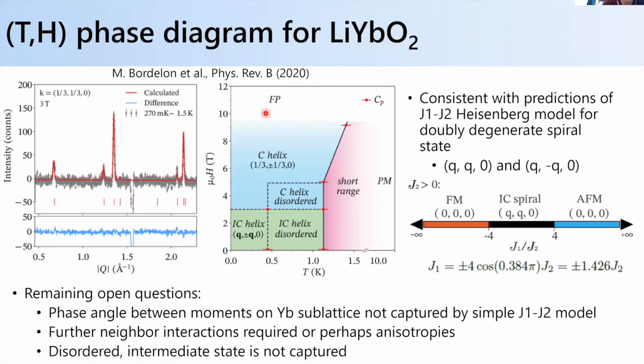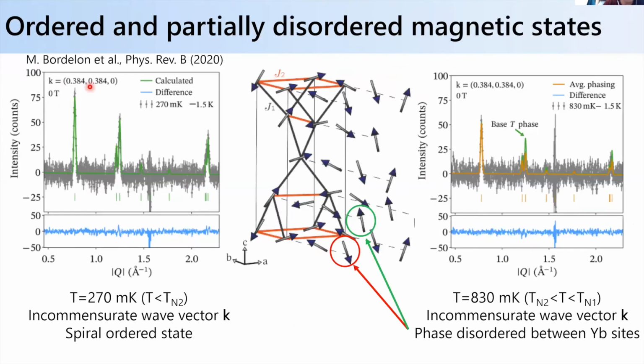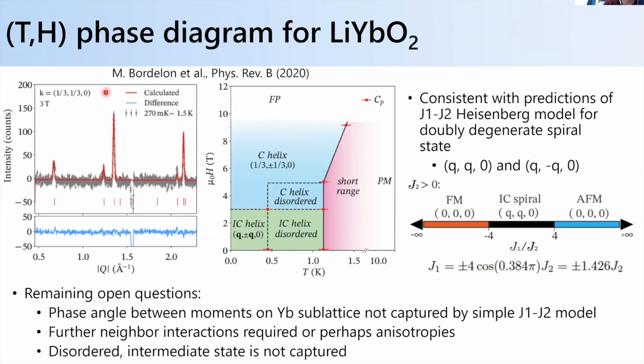And so what Mitchell did then is he also applied a magnetic field, and he looked at what happens as you apply magnetic field in the system. What we find is that you still have a helical order, but the propagation vector locks in to a commensurate vector. So it goes from this 0.384 wave vector to a third 0 when you apply a 3 Tesla field. And so the phase diagram is somewhat summarized here as a function of field and temperature.